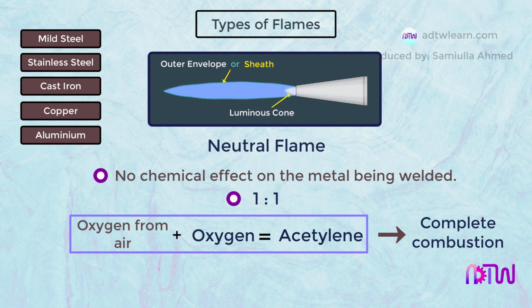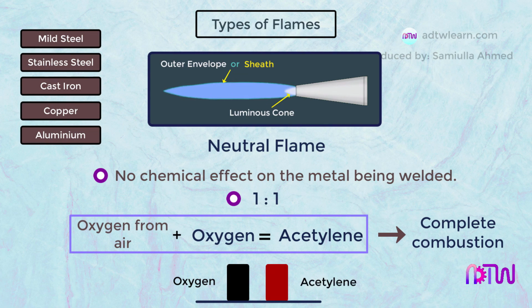The neutral or balanced flame is obtained when the mixture of gas consists of approximately 1 volume of oxygen and 1 volume of acetylene. It is obtained by gradually opening the oxygen valve to shorten the acetylene flame until a clearly defined inner cone is visible. For a strictly neutral flame, no whitish streamers should be present at the end of the cone. In some cases, it is desirable to leave a slight acetylene streamer, or feather, to ensure that the flame is not oxidizing. This flame adjustment is used for most welding operations and for preheating during cutting operations.